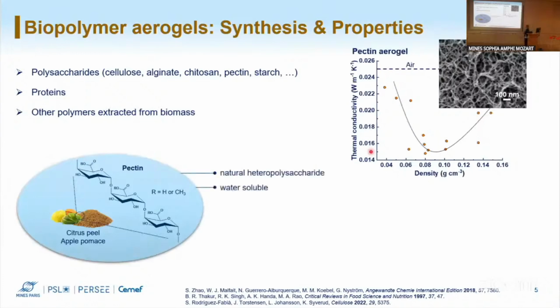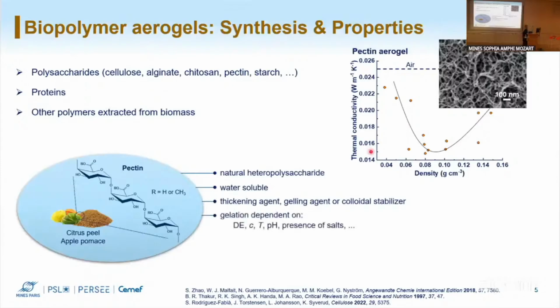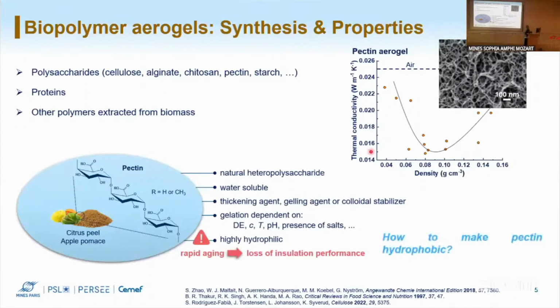It's a natural heteropolysaccharide. It's water soluble. It's used in the food industry for its gelling properties, and these properties depend on the degree of esterification of pectin, on the pH of the solution, and other parameters. Pectin, because of its structure, is highly hydrophilic, and when we want to use it for materials engineering, we notice that there is a very rapid aging, probably not seen with a lot of biopolymer aerogels, and we have loss of the insulation performance that we can see in the graph above. So the first question that we have in my thesis is how to make pectin hydrophobic.